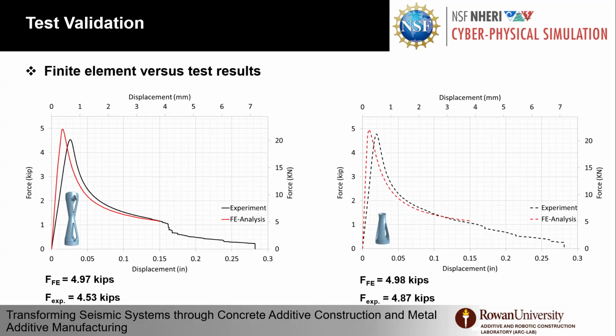So we machined it, removed the damaged plates and tested again just to verify. We were scared that when testing a second time we would have less capacity and could not justify it, but it was about 5% extra on the high side. We actually are now applying for funding to, instead of just optimizing the fuse and printing it, print different specimens for compression testing, tension and low cycle fatigue, to understand the material at the material level before we go to the fuse stage. So optimization of material and process, because the process affects the material and the material affects the process.